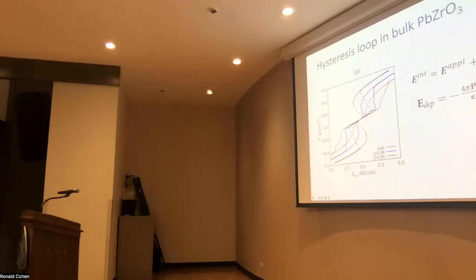So here we just use the bulk lead zirconate, but we introduce depolarizing field, and that brings the internal field. Well, the internal field here in the sample is going to be the sum of two contributions, the applied field and the depolarizing field. And we can see that actually if we introduce this term, we can obtain the negative slope, we can obtain that negative susceptibility, but this is bulk simulation.